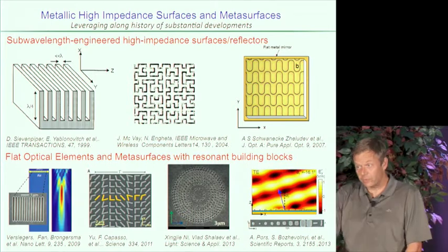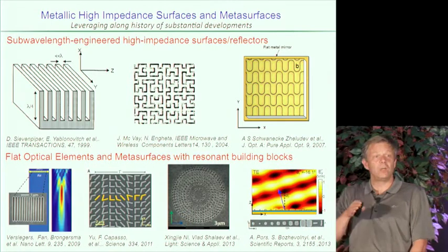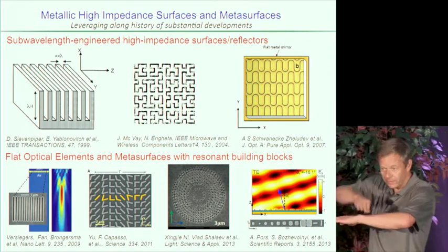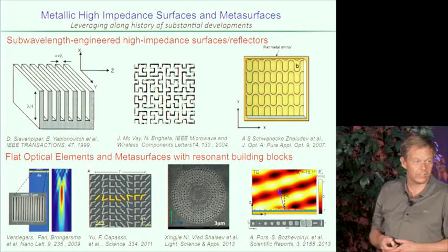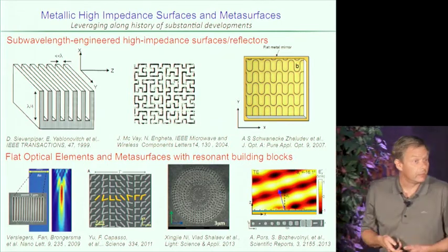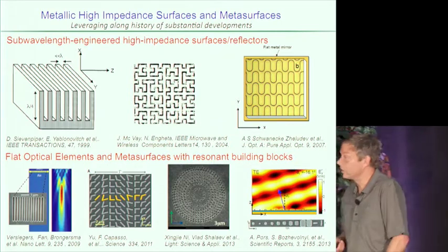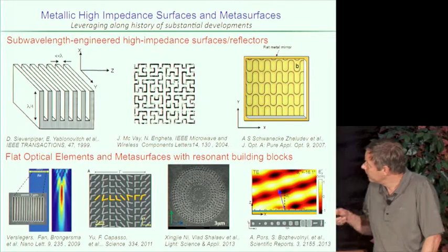And as you change the reflection phase, you change the standing wave pattern of the light coming into the mirror and reflecting off of it. You can change exactly where your maxima of the field intensity are, and thereby where the strongest light absorption or light-matter interaction will take place.